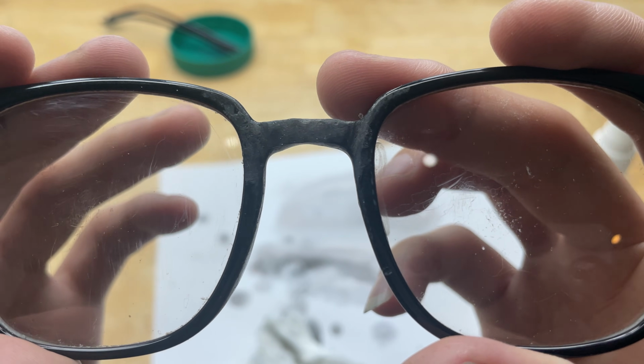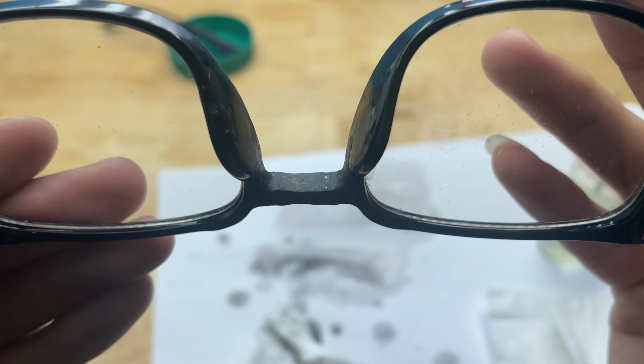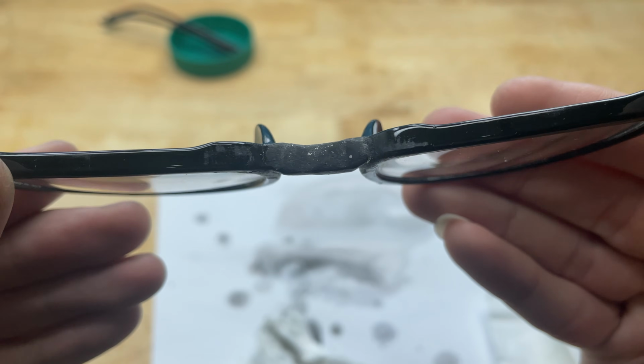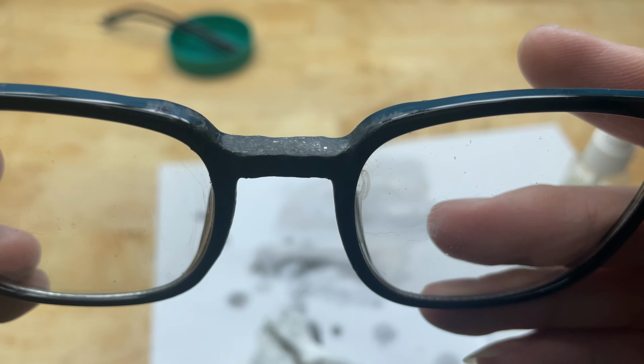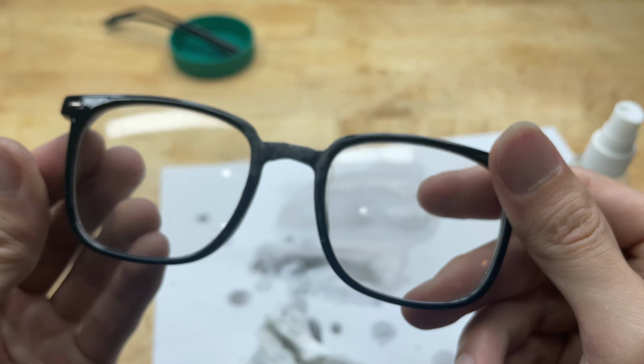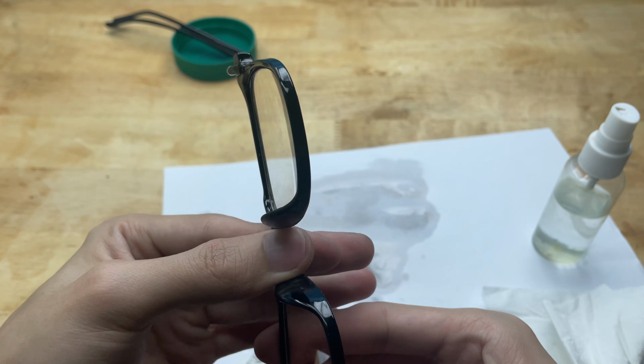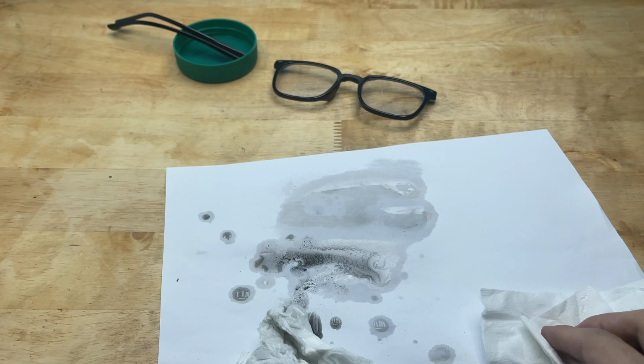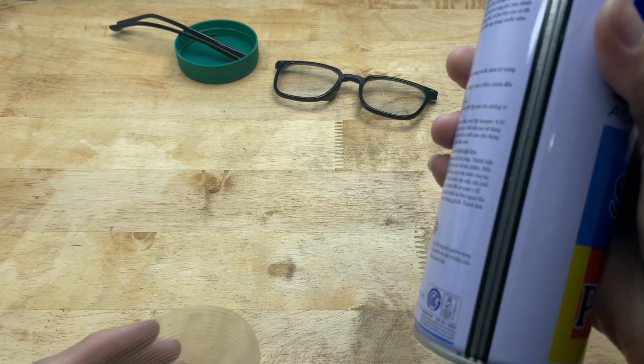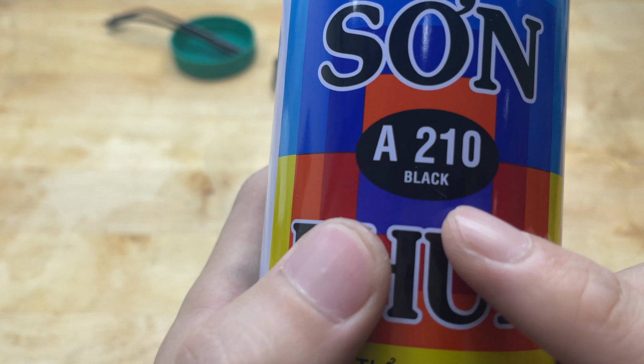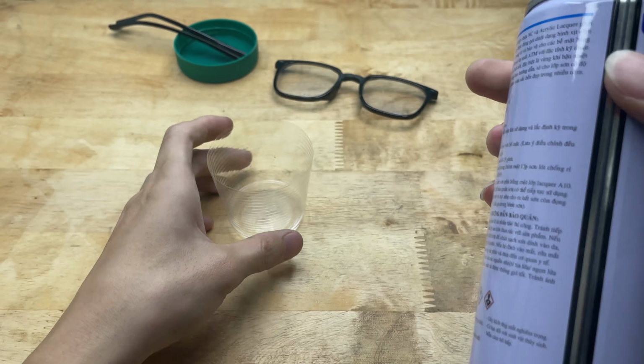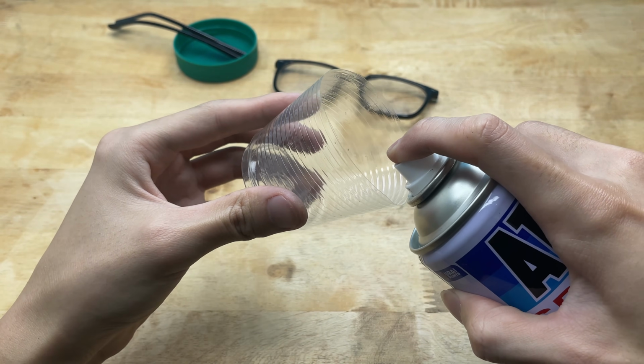The scratches left from the coarse sanding are largely removed, and the repaired area blends more naturally with the surrounding frame. The transition between the original plastic and the repaired section now appears much cleaner, giving the bridge a refined and solid finish. After the surface has been fully smoothed, I will repaint the repaired area to restore the overall appearance of the glasses.